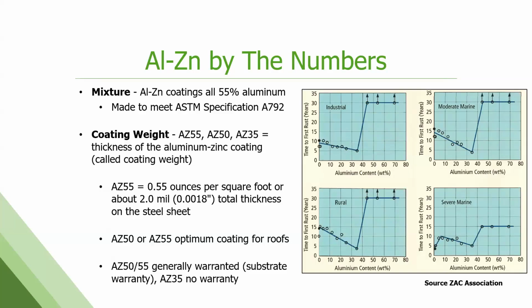Now, why 55% aluminum, right? Trust me, some very, very smart people at Bethlehem worked for many years getting this ratio just right. And the graphs on the right there show you that, at a lower aluminum content, performance, time to rust, not so good. As soon as you get in that 45 to 55% range, you get this huge jump up in performance and resistance to corrosion. So that's how they landed on 55% aluminum, 45% zinc. The ASTM specification for this product is A792. You will see that called out in specs.